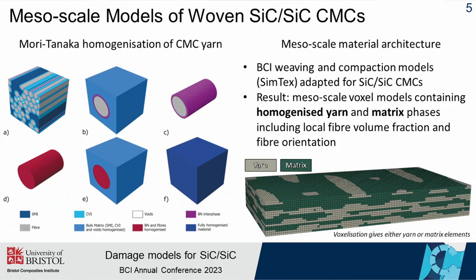So when applying this to these SiC/SiC CMCs, the homogenization has to be done in several steps. Firstly, we combine the fiber coating or interface, which in this case is the boron nitride interface, with the fiber itself and do a first step homogenization. And then later, so this is one major assumption in the work.